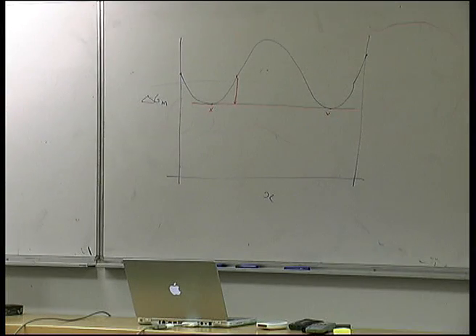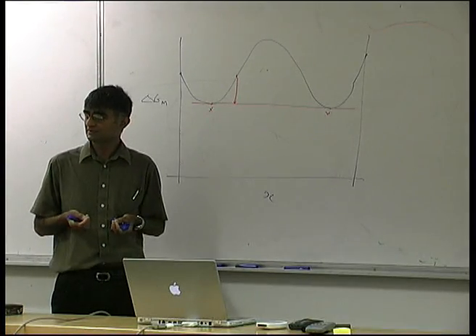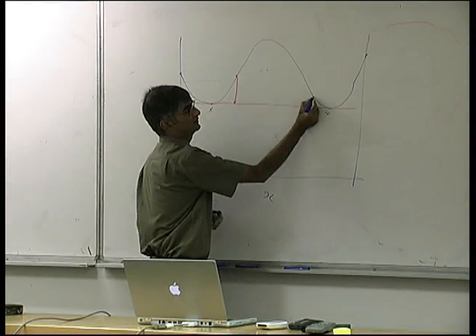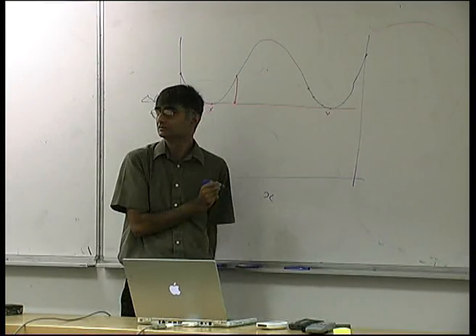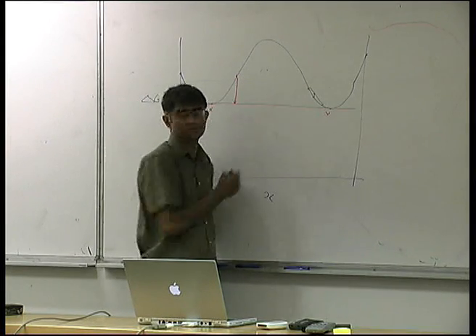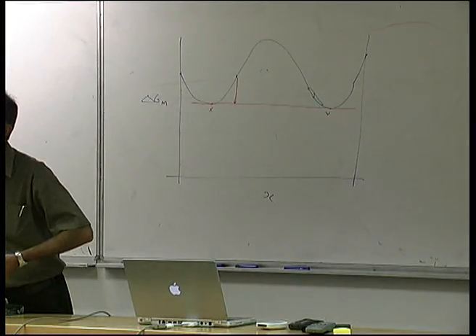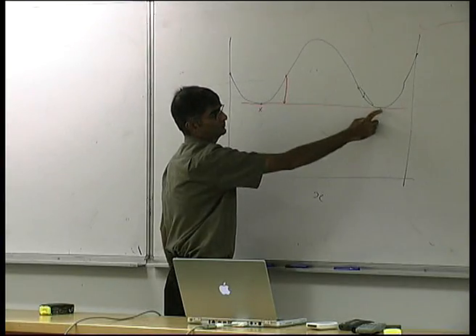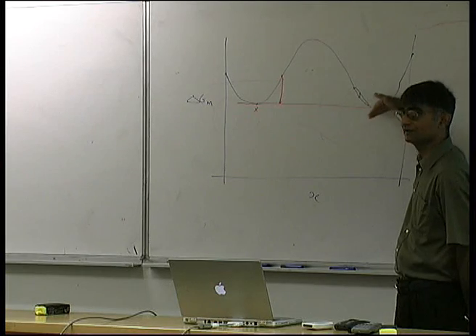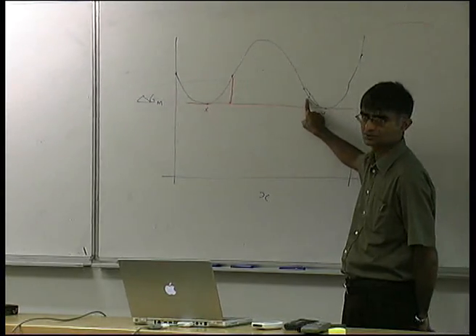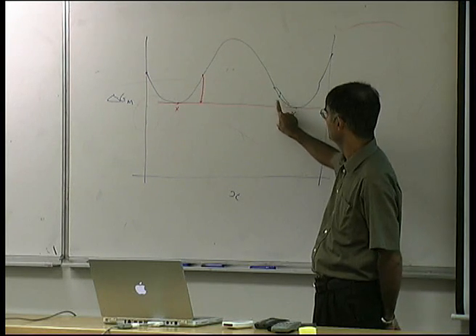The interesting thing about this curve is that although there is a free energy reduction when a solution goes to the equilibrium mixture, to start off that process is quite difficult. If I look at a composition and want to change it slightly to an A-rich and a B-rich region, joining up those two nearby points shows there is actually an increase in free energy. So to create an A-rich and a B-rich region initially, you actually have to increase the free energy.